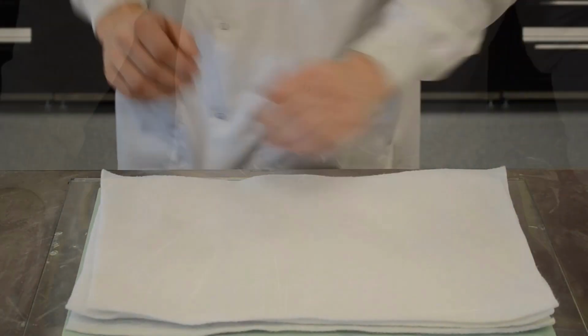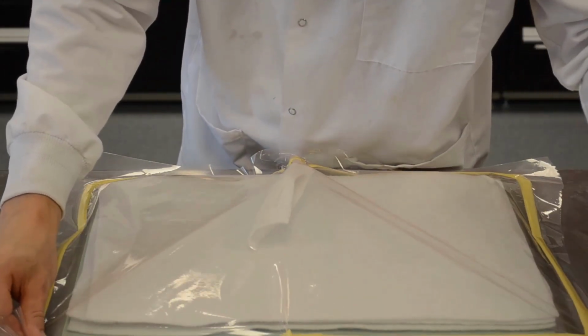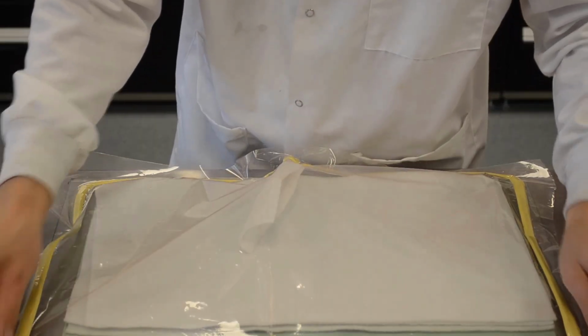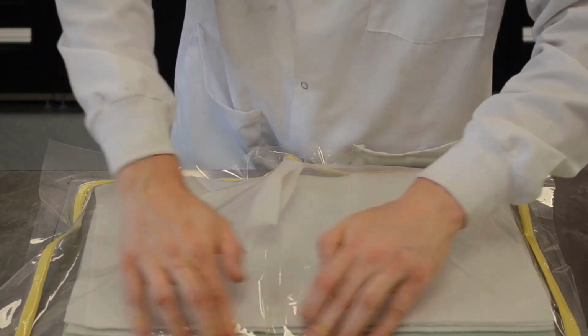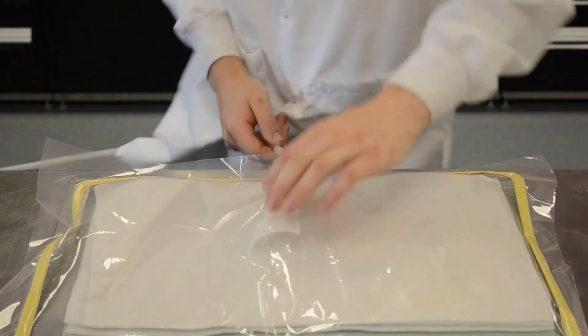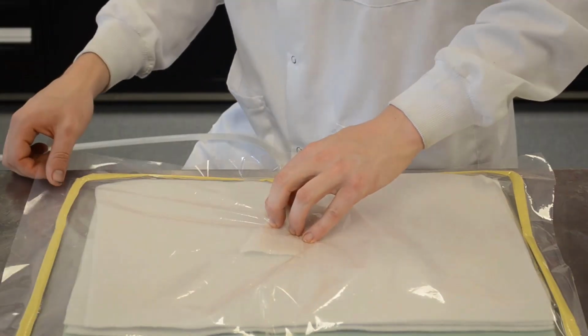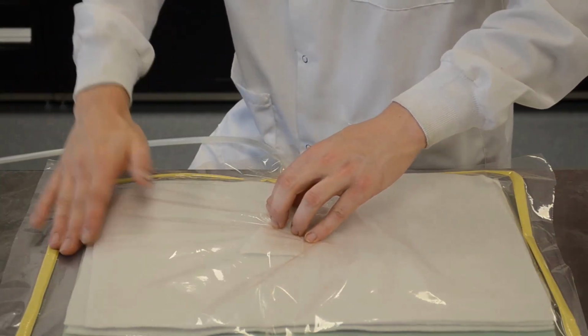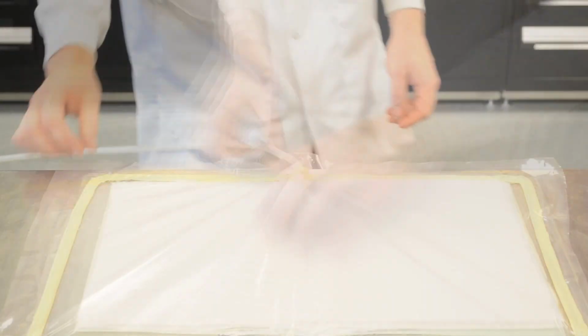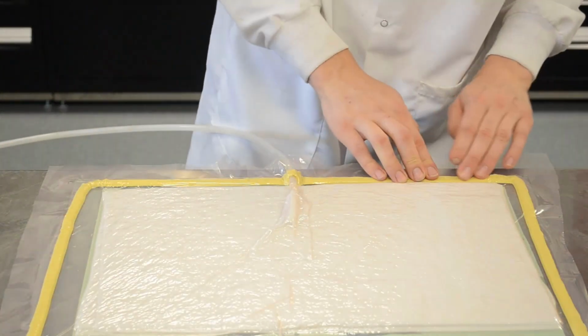We will locate the vacuum port near the center of the layup under some additional layers of breather cloth to ensure good airflow. Around the perimeter of our layup, we will place sealant tape to form an airtight seal to the tool. We will place the vacuum bag over top of our layup and seal it to the sealant tape. We will then pull vacuum on the layup as it cures.